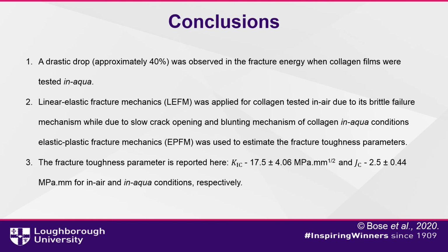Conclusions. Three basic conclusions can be drawn from this study. A drastic drop, approximately 40%, was observed in the fracture energy when collagen films were tested in aqua. Hence, while designing collagen-based materials, all the mechanical testing should preferably be performed in-aqua conditions.